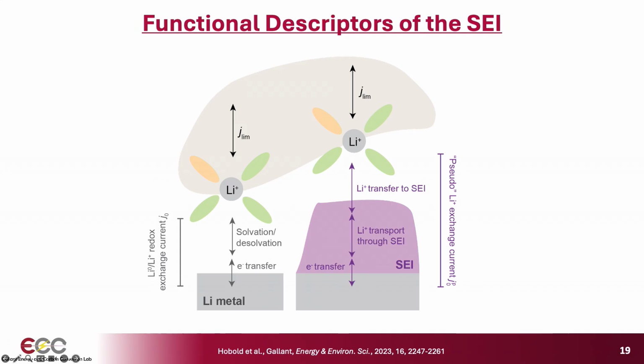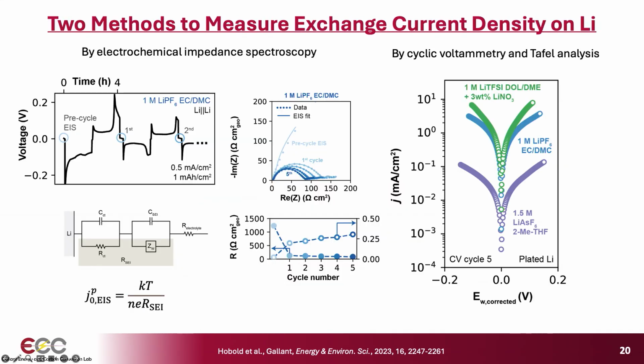So we posited that this parameter, if we could figure out how to measure it on a reacted lithium surface, would actually tell us something sensitively about the SEI, and perhaps even tell us how exchange relates to Coulombic efficiency and reversibility. So we set about developing 2 methods to quantify the exchange current on lithium.